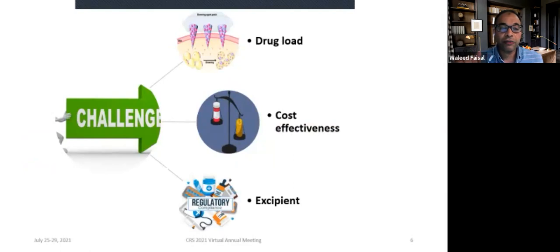However, there are a lot of challenges for this technology. The first challenge is the drug loading. As we know, the size of the microneedle is very small, so you are limited in the amount of drug, but then you need the microneedle to have this structure of sharp microneedles. It's mostly formed by the excipient, the polymer itself. And the polymer has to be around 90% or more to give this strong and sharp structure of microneedles, and this limits the amount of drug loading.